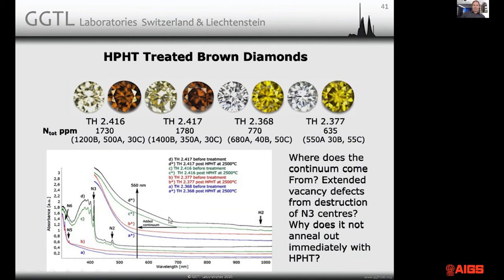The lower N3 center samples after HPHT treatment actually had more C center content than the N3 center samples. So it's certainly not C center related. And then if you look at the spectrum, there's something significant to notice. The N3 center and the N2 center are absolutely absent from my UV visible spectrum. So I heard somebody saying, yeah, well, it's just a continuum overlaying the N2 and N3 center, which is absolute nonsense. The N2 center would be clearly visible; if you have some C centers in an N3 center diamond, you will still see the N2 and N3 center after such treatment.